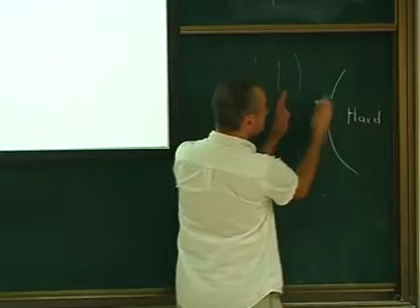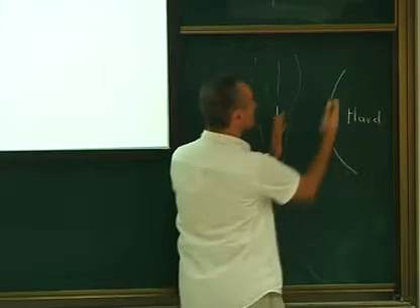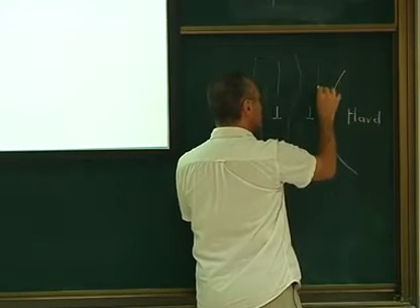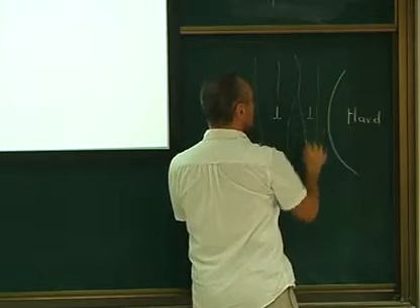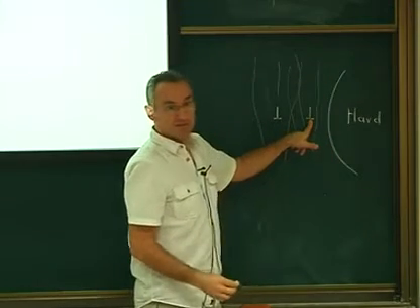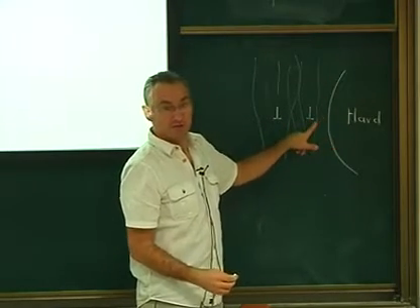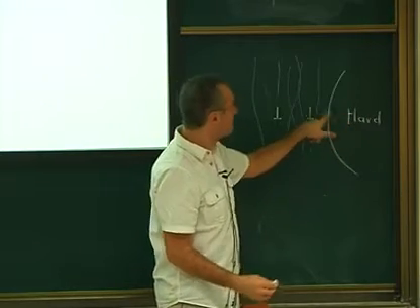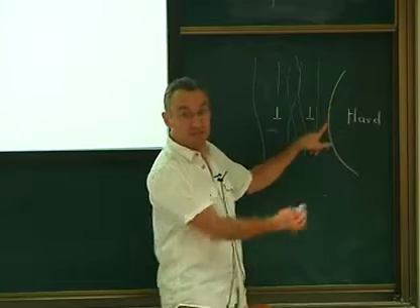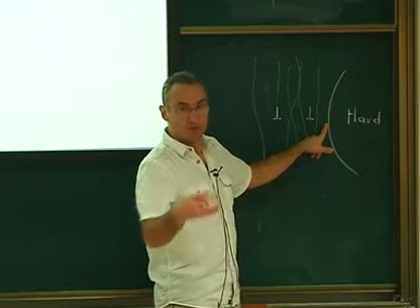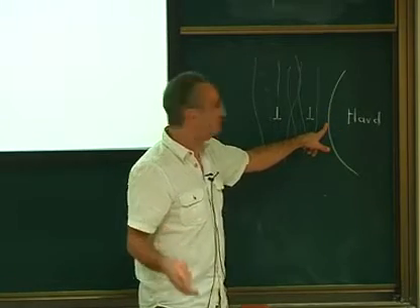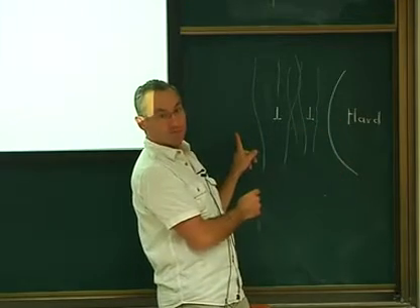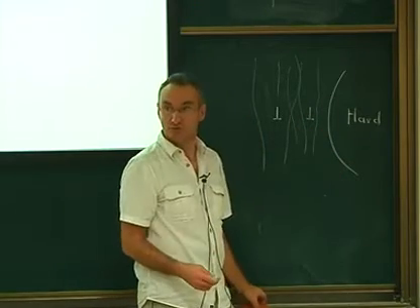When it comes here, it will not be able to distort the network anymore because now this will be very rigid. So locally, the dislocation will be here, and the plane cannot be distorted, so it will be like this. So the stress field is modified. This is what we call an image force. The dislocation will feel some image force due to the change of moduli. Just because this is not the same medium as that one, there is an image force, a back force on your dislocation. I will explain why it is called image force, which is a bad word actually. Image force on the dislocation that will push the dislocation out of the hard particle. Okay? You get the idea?